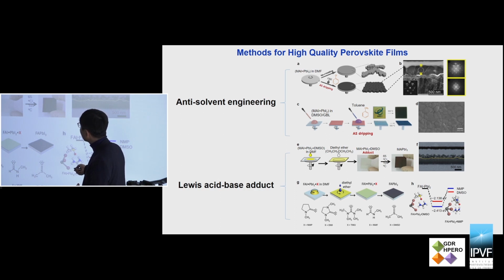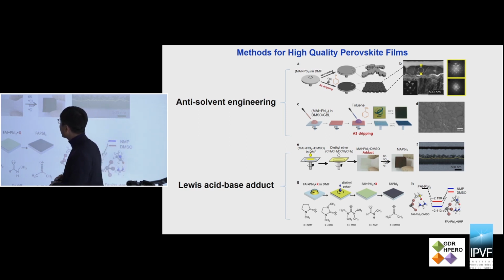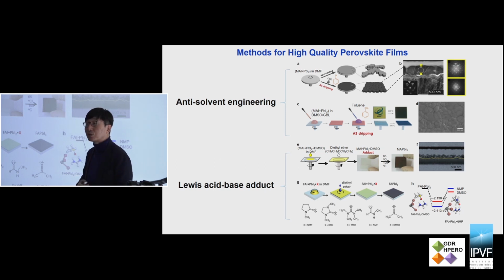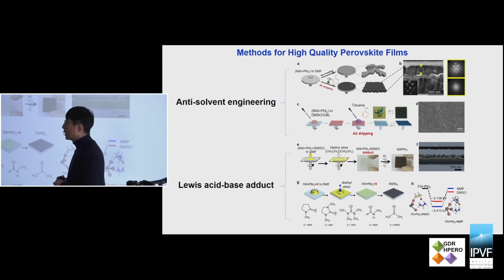If you take a look at the precursor material, PbI2 is a well-known Lewis acid, and the polar aprotic solvents DMSO and DMF can be used as a Lewis base. So in inorganic chemistry, if you react a Lewis acid and a Lewis base, you can have a weak chemical bonding, a Lewis acid-base adduct compound intermediate. So we utilize this intermediate to control the crystal growth of perovskite.